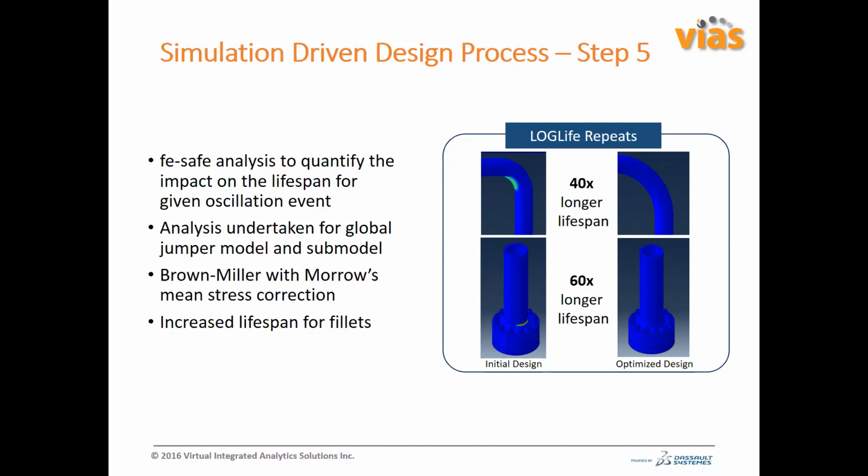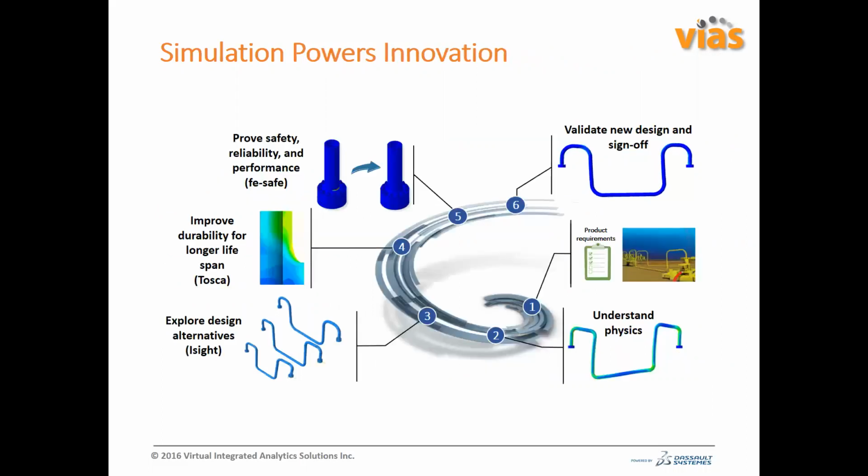Another thing is, if you do a fatigue analysis, that's the first cut analysis. If you find there is a problem with the fatigue life, you can always do an engineering critical assessment, which is a fracture mechanics based fatigue and fracture assessment. You can assume the initial flaw size, and most of the time it depends on the non-destructive testing that you are doing, so what is the sensitivity of that testing? Any crack that you cannot detect, you will assume is the initial shape of the crack, and then do a fracture mechanics analysis.